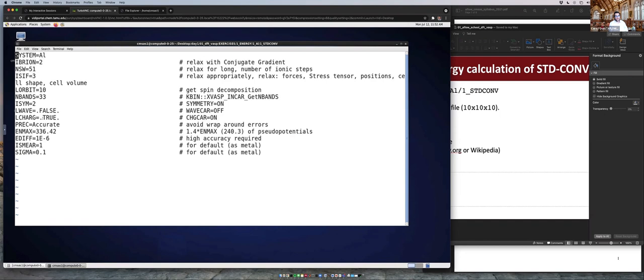PREC equals Accurate. Remember we're working in the reciprocal space, so we're going to be using some Fourier transforms to solve our system. Accurate says that we want our mesh for the Fourier transforms to be as dense as possible. ENMAX is the energy parameter I described earlier, which tells how large that basis set of plane waves should be. We're going to include a number of terms up to that energy cutoff. VASP gives us a default for each pseudopotential, I'll show you in a second. In this case, it's 240.3 eV, and we multiply that by 1.4